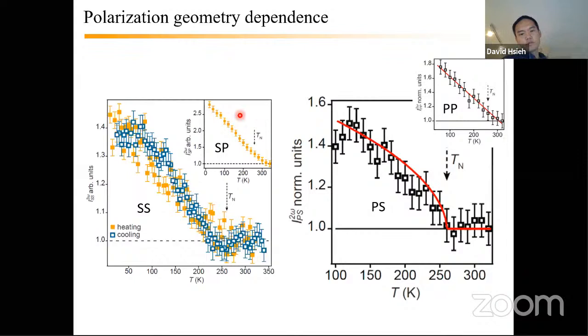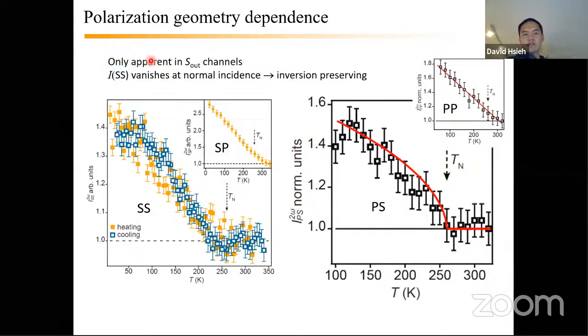It was at the beginning an experimental mystery as to why we only see it in these S out channels, not in the P out channels. And moreover, I should mention we did angle of incidence dependence measurements also below T_N, and we found that the intensity vanishes at normal incidence, and so we know that this extra piece that emerges below T_N is not coming from the electric dipole channel. So it doesn't break inversion below T_N.